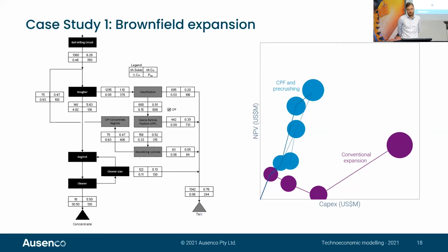And we put together a technoeconomic model that did the full mass balance of solids and copper around the circuit, and produced an NPV on CapEx graph, which you can see in the bottom right there. The size of the bubbles is proportional to the copper production, and it just plots the NPV versus the CapEx. And you can see the difference between the conventional expansion that they were looking at for this plant versus the coarse particle flotation and the pre-crushing. Much lower CapEx required and much higher returns from the technology.